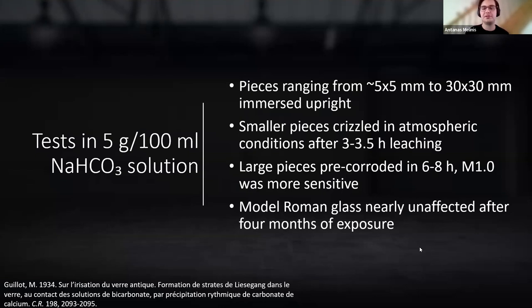We took an idea from a study conducted almost 90 years ago, referenced at the bottom, where chemist Maurice Guillot filled laboratory vials with a saturated solution of sodium bicarbonate, otherwise known as baking soda. And he observed that the insides of the vials developed thick, laminated corroded layers within weeks or months. To my knowledge, this technique of corrosion in weak alkaline solutions between pH 9 and 8 hasn't been repeated in later reviewed publications. So we decided to try it out.